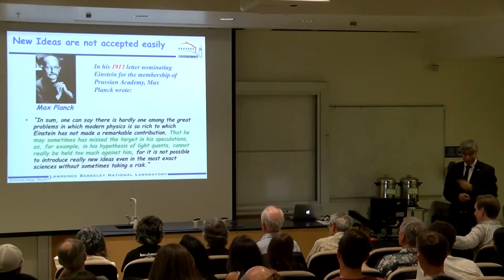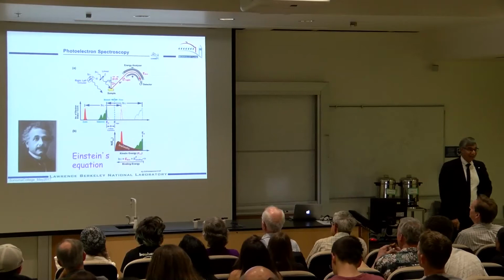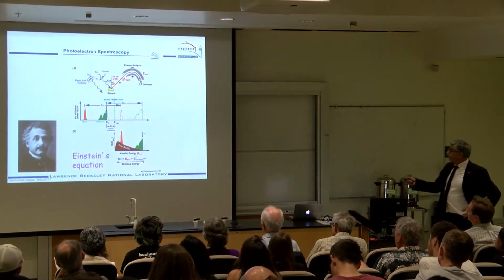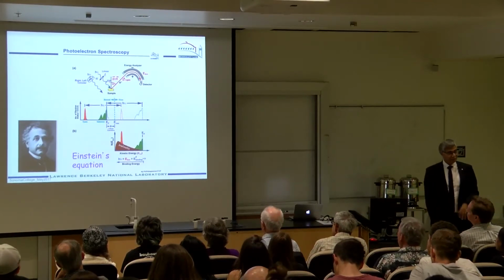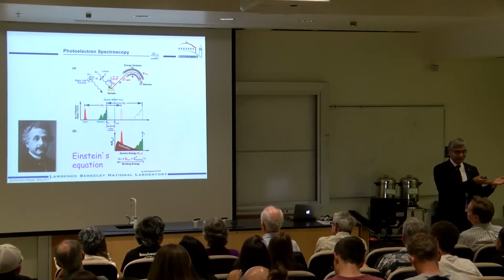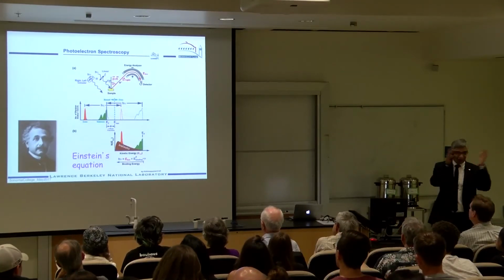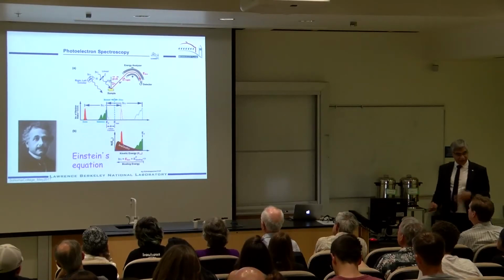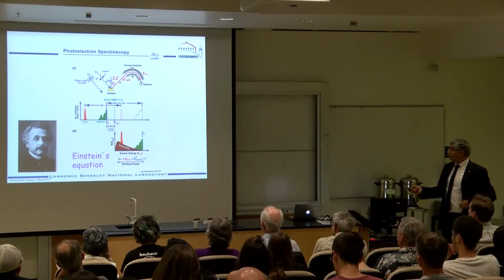So now the same physics continued, and this is what we study. If you take a material and you shine a light on the material, the electrons get popped out. It has to be in vacuum, because in the air they will just get scattered by the air and they won't go anywhere. So you have to do the experiment in a vacuum. You have some kind of detector, an analyzer, which picks up the distribution of the electrons.